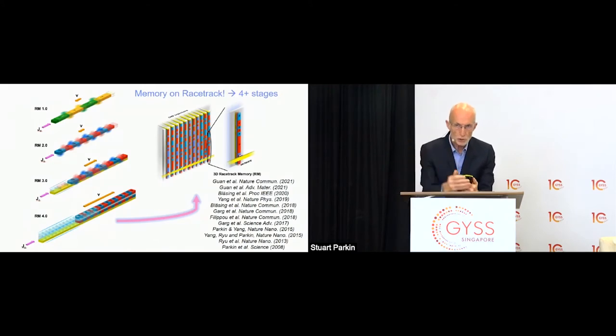We then moved, in racetrack 2.0, to a superlattice of cobalt and nickel, in which the broken symmetry causes the magnetization to be perpendicular and the domain walls to be 100 times narrower. Nevertheless, the domain walls move with current under the same principle that the current is spin polarized in the material and develops spin transfer torques onto the domain walls.